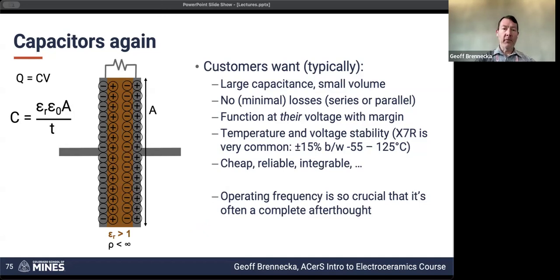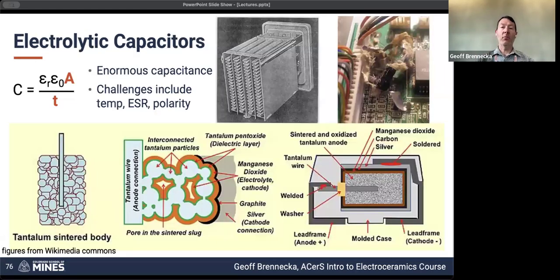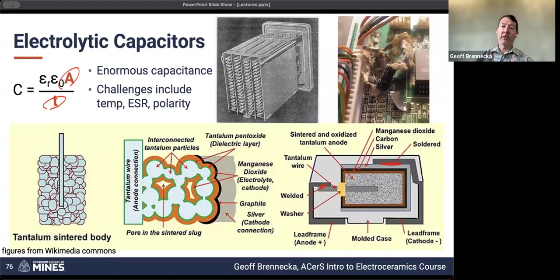So if we're going to be building these capacitors, one option is we would just want to absolutely maximize the total amount of area and do that with as thin a layers as possible. So one of the early technologies for taking advantage of this is you start with an extremely large surface area of some sort. So one example here is just basically foil that's been folded and then oxidized. If you take aluminum and anodize it, then you've grown an aluminum oxide layer, and that aluminum oxide layer is a dielectric. So it's a great insulator. It's not going to pass a lot of charge.